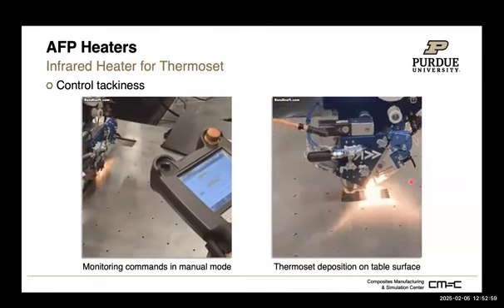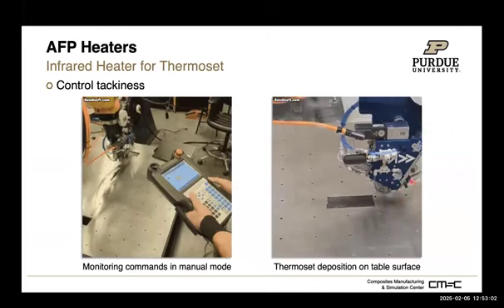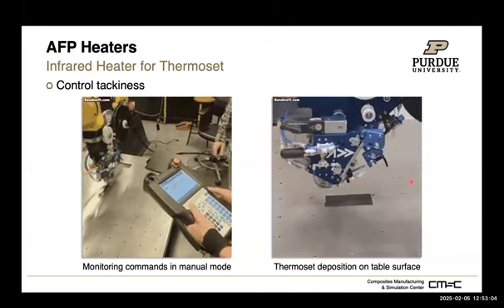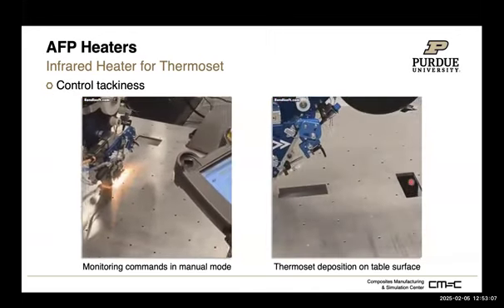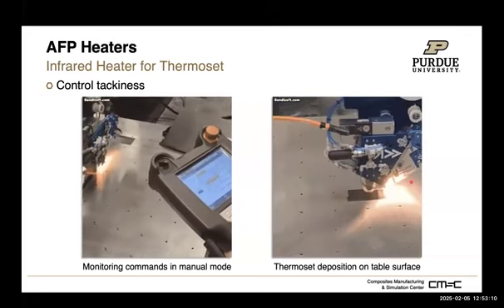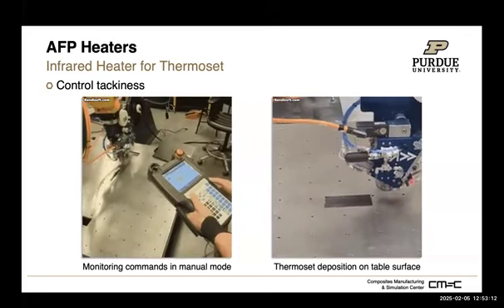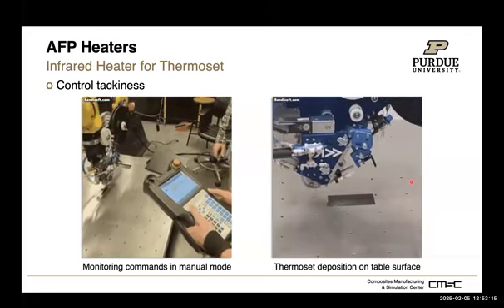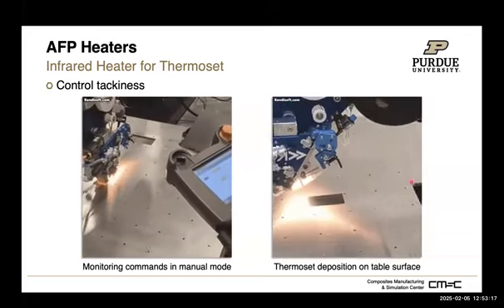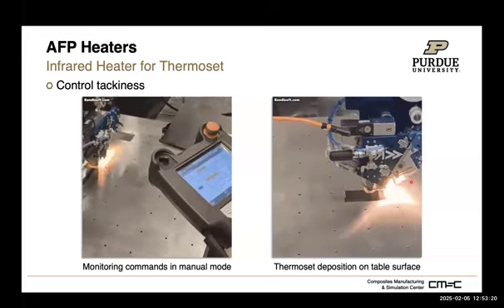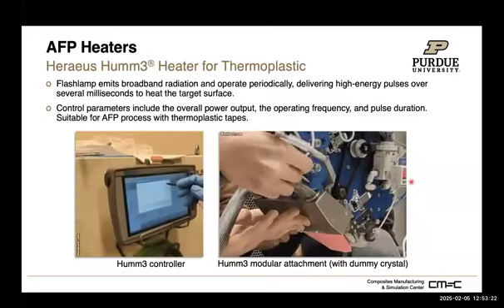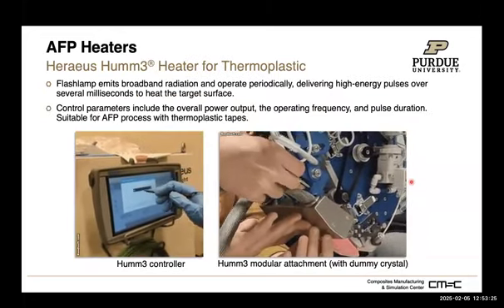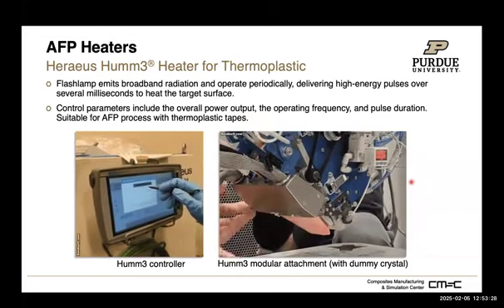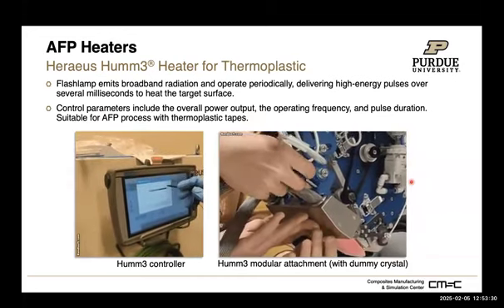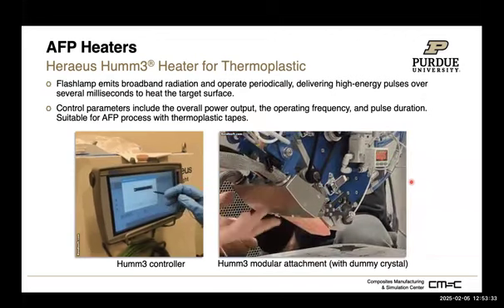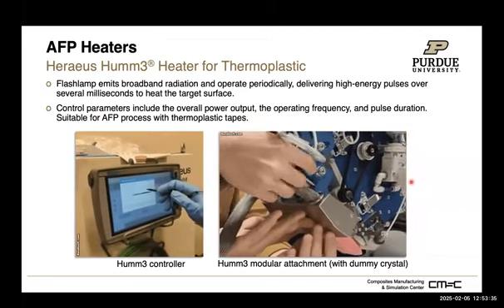One difference in this technology is that we need to establish some tack of the tape when we do the placement. So we've also been looking at what the right heating would be. Using an IR heater is pretty standard for this technology when working with thermosets. But there's also a very cool heating device we are installing, a Heraeus Humm3. This is not something like a laser, where we need lots of protections and lots of times we hit lots of roadblocks in the university